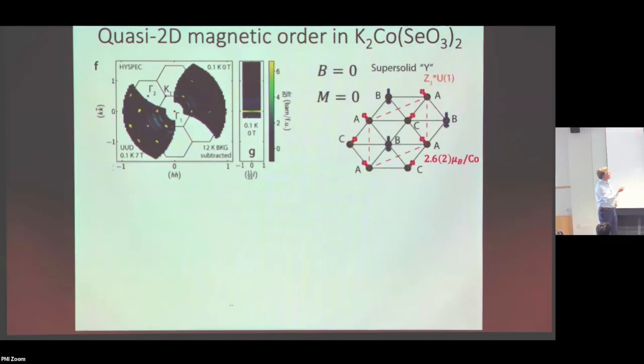And so we can develop a picture for the spin structure, which actually looks something like this. It's not a unique picture, but it does describe the data. And so the interesting thing is that the moment per site is heavily reduced from the full magnetization. And also, I found it very interesting, and still do, that there's really no peak in the middle there. The peak in the middle would correspond to a uniform magnetization on the triangle lattice plane. But that one is completely suppressed.